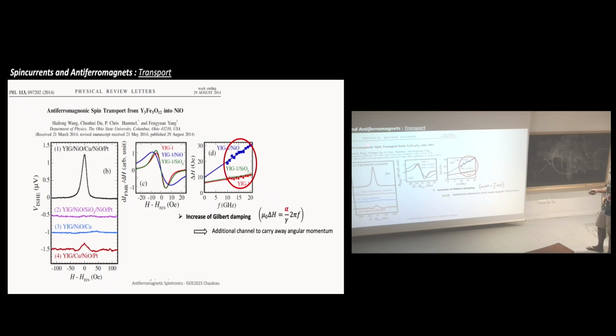This study has been very thorough. They checked a lot of things. So this is when the NiO is directly in contact with platinum and the YIG, and then inserted, for example, copper in between. And copper has a very long spin lifetime. So if you have a spin current which is going here, it crosses copper without any problem, then goes to the other NiO and can be detected in platinum. Then they checked if they insert silicon oxide, nothing happening. If you have only copper, they don't measure anything. And if you have copper, then NiO, platinum, then they measure a tiny signal. So that was really a proof also that antiferromagnetic oxide can convey spin angular momentum. And since it is an oxide, the way to convey spin angular momentum is through magnetic excitations, so through the magnons.